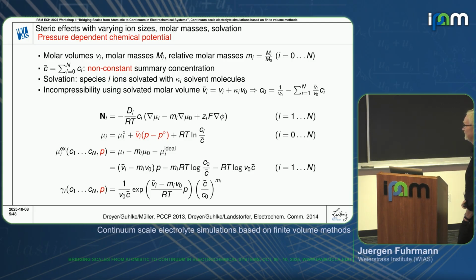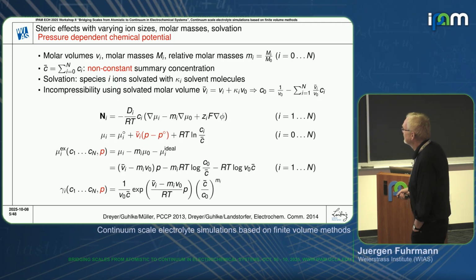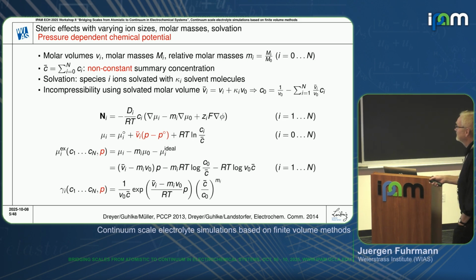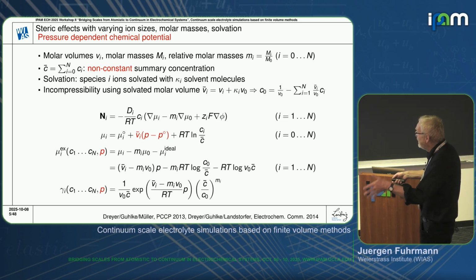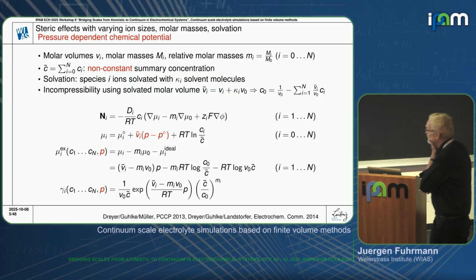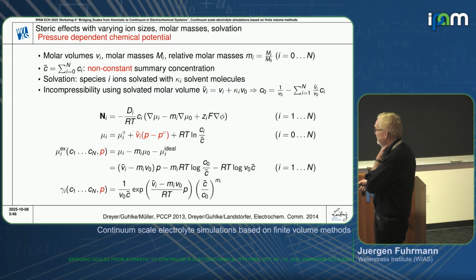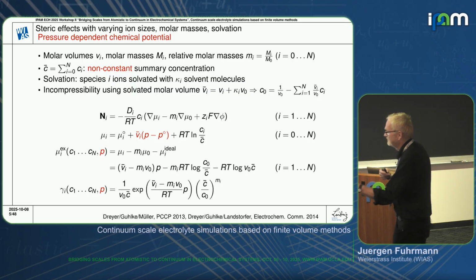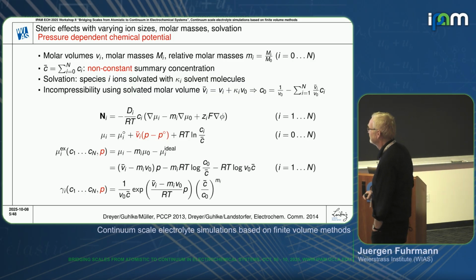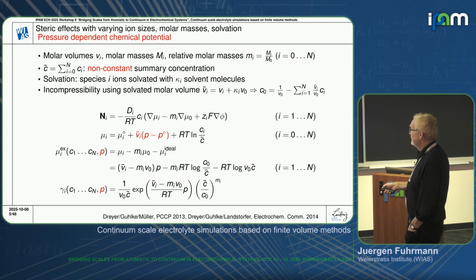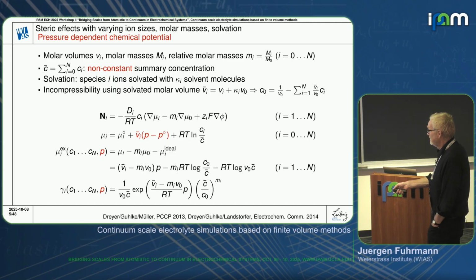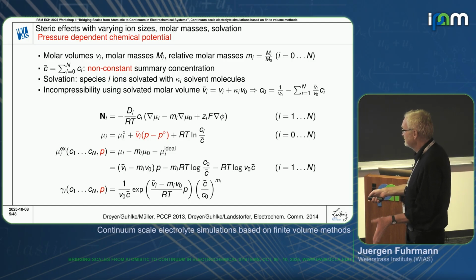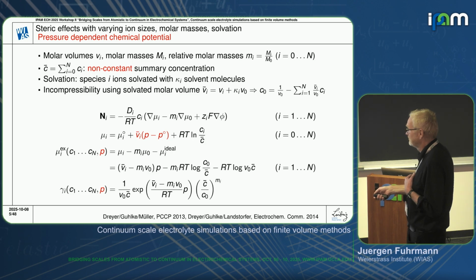So if we write these molar fractions, we need to be aware that this C bar then depends on all other concentrations. And the, let's say, main contribution from this work of Dreyer et al. is the fact that once we derive these chemical potentials from the corresponding free energy functionals, we need to take care of the pressure. Because if we have exchanging volumes, then we get an influence on the pressure. And that means that our excess chemical potential, which we can calculate in this way, will, in addition to all the species concentrations, also couple to the pressure.